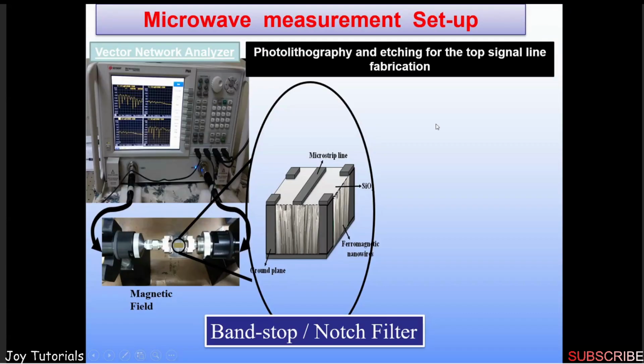Now, coming to the measurement of these devices, I have a vector network analyzer in my lab. When we design this with the nanowires, we put this nanowire-containing device here. We feed the electromagnetic wave from port 1 and let it go to port 2, and we see the scattering matrix. The scattering matrix is a reciprocal matrix, which has the voltage ratio and the power ratio, through which one can define the filter or the phase shifter characteristic, or any device as a whole.